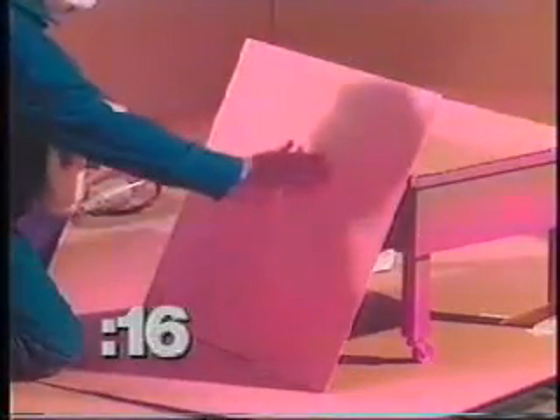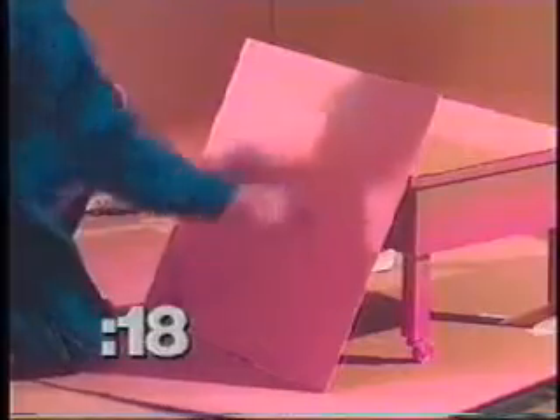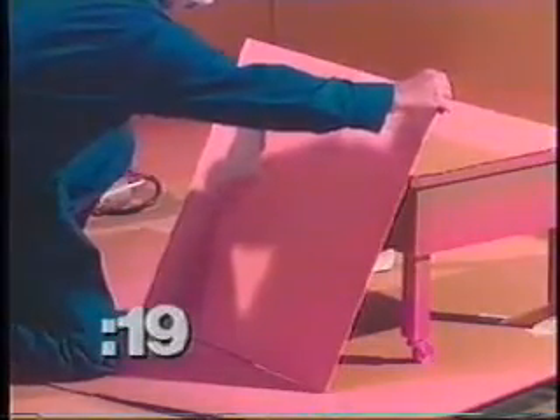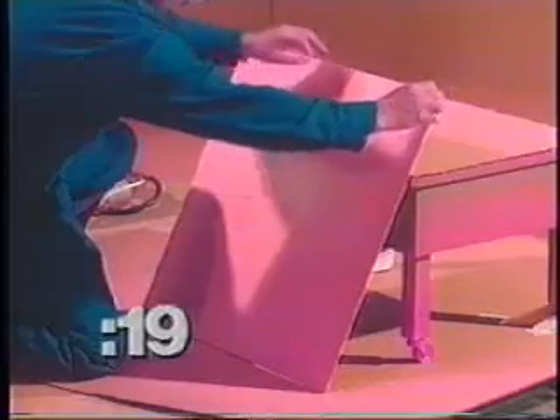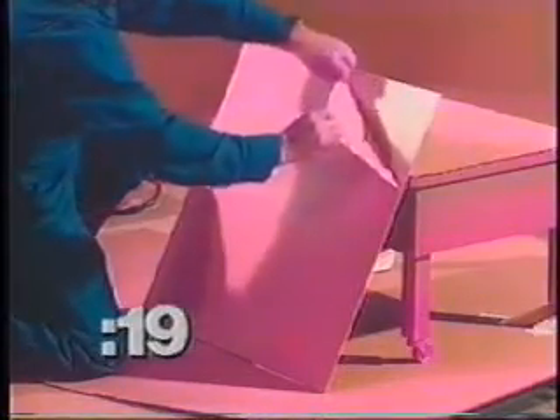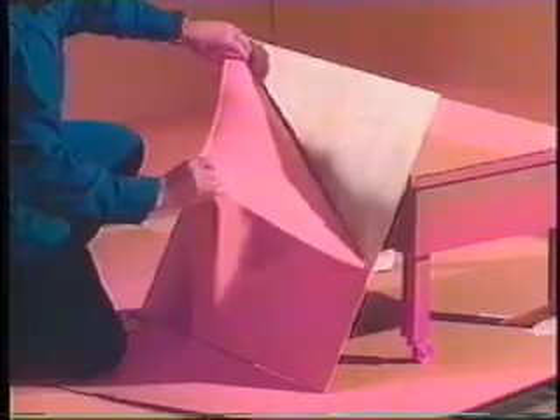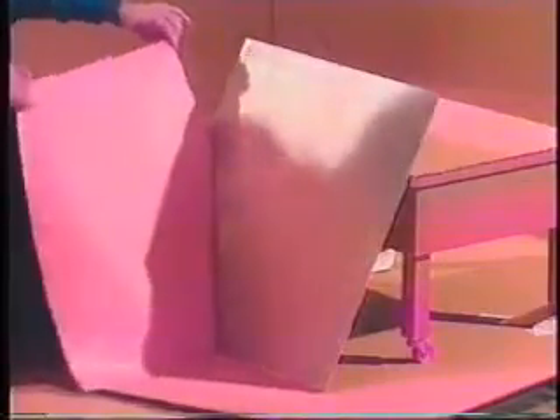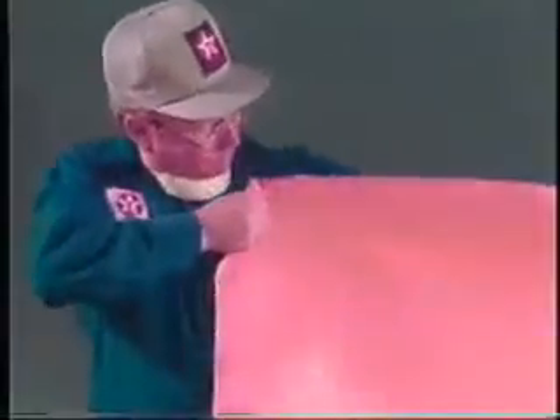This clock demonstration shows how fast a cure can be accomplished. Envirolastic is free of VOCs, thus contains no dangerous solvents, therefore no flammability and no odor. A bond breaker was applied to this sheet of metal to allow the material to be pulled away from the surface. As you can see, it dries very quickly. It's flexible and it's tough. Tests show high tear and abrasion resistance.